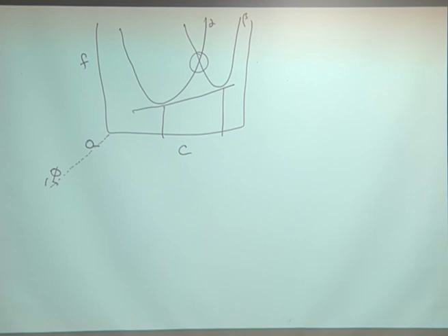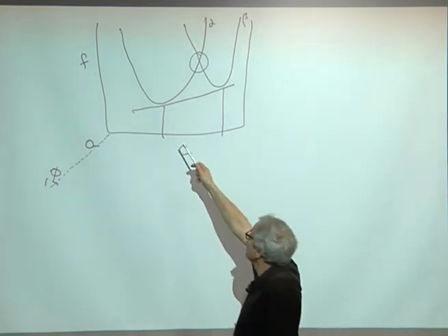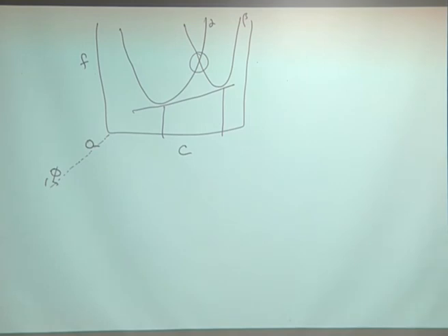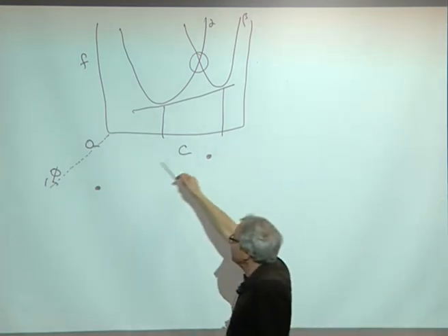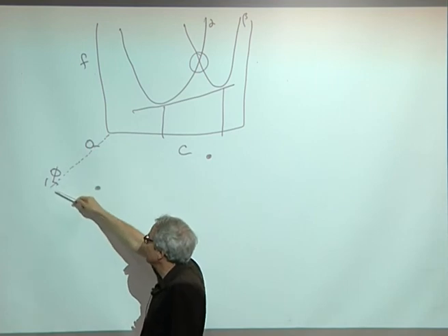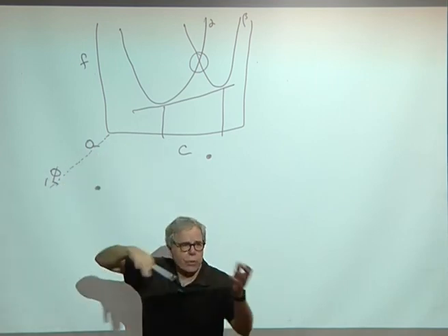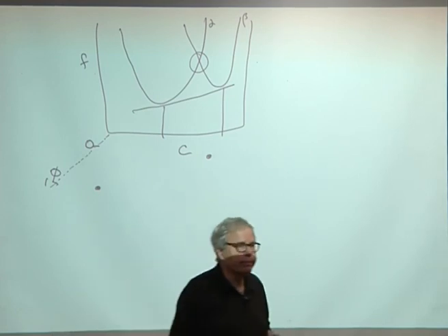And when it's 0, you sit down here. And when it's 1, you sit up here. And those minima sit in this 3-dimensional space. So you have one minimum that sits out here, and you have the other minimum that sits out here. And when you project it into that 2-dimensional space, it looks exactly like this. And since it's now continuous by this way that you've put these two free energies together, you can take all the derivatives, and everything else works.